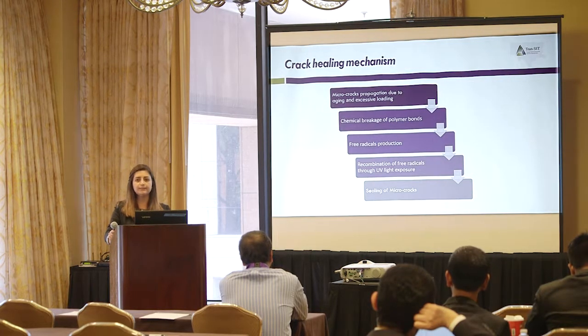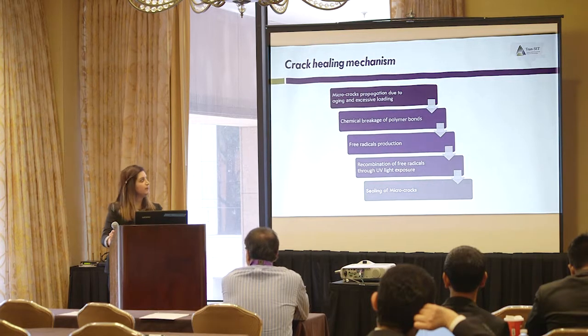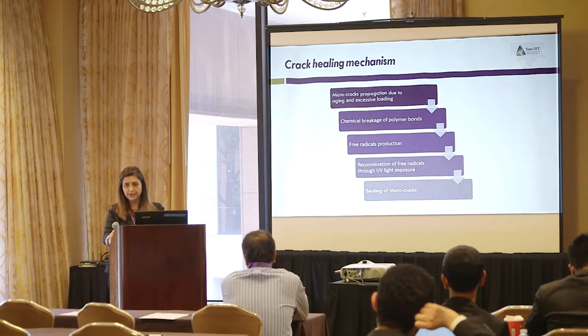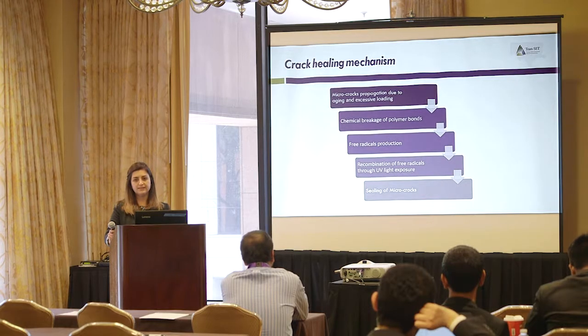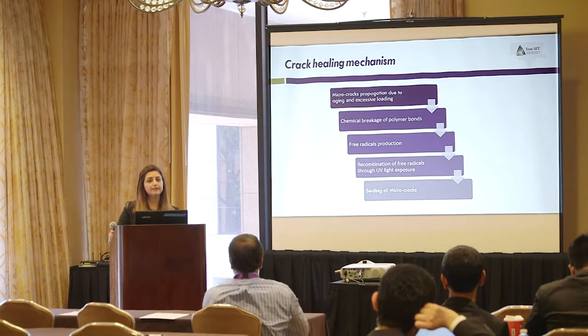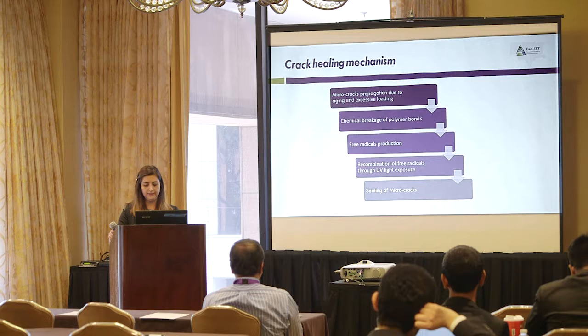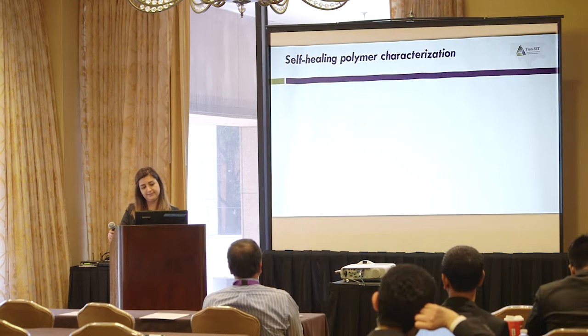The crack healing mechanism is like this: when microcracks appear in asphalt pavement, chemical bonds of the self-healing polymer are going to be broken, and free radicals are going to be produced. These free radicals are going to recombine with UV light exposure, seal microcracks, and stop propagation of the cracks in asphalt pavement, which eventually can lead to an increase in service life of the pavement.